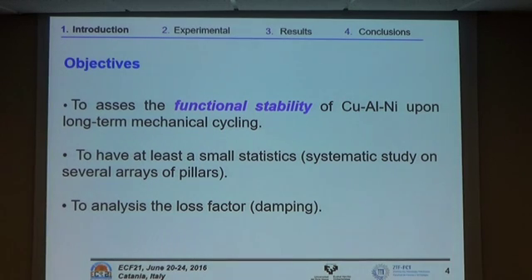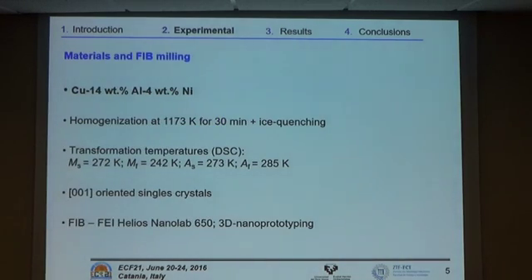We have prepared several arrays of pillars, and then in particular we have studied the damping capacity of this material. The material we have used is the copper 14 weight % aluminium and 4% nickel shape memory alloy, which was homogenized in a standard treatment for half an hour and then ice quenched. The transformation temperatures as determined by DSC are the following. Mainly they are in austenite state at room temperature. We have used oriented single crystal with the 001 direction upwards.